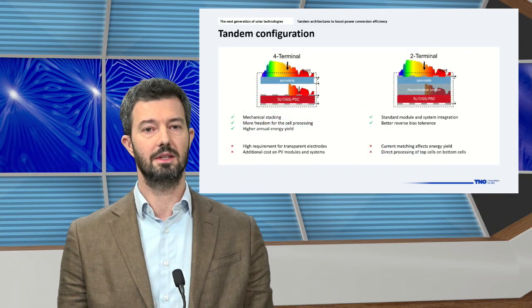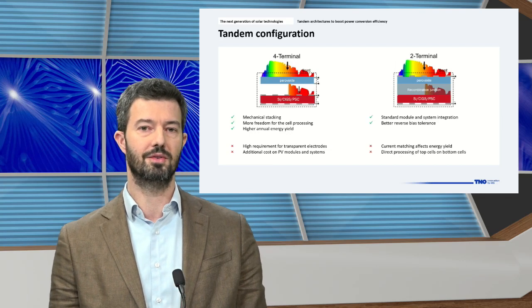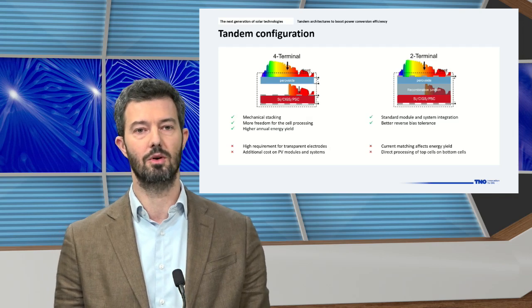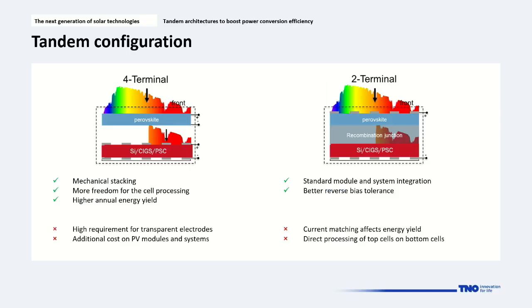So how do you construct the tandem architecture? Essentially, worldwide, there are two different structures that people are really focusing on, what we call 4-terminal and 2-terminal architecture. In the case of 4-terminal, you simply stack the top cell on top of the bottom cell. This gives you a lot of freedom in how you make the top cell, for instance, and potentially also gives higher energy yield production. The disadvantage is that typically you have more layers to make, so there is a little bit more parasitic absorption that can affect the production of the bottom cell. And on a system level, because these two devices are electrically independent, it potentially means additional cost.